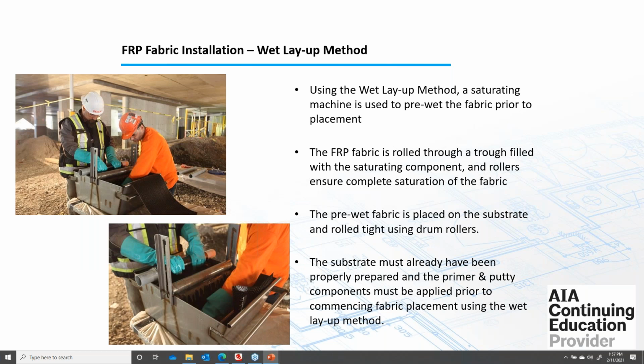The wet layup method is slightly different. In the wet layup method, the saturating machine is used to pre-wet the fabric prior to placement. The purpose is a full impregnation of heavy fabric fibers using a low viscosity epoxy, but the technique could also be used for regular fabrics. The FRP fabric is rolled through a basin filled with the saturating component, and the rollers ensure complete saturation of the fabric while removing excess epoxy. The pre-wet fabric is then placed on the substrate and rolled tight using drum rollers.